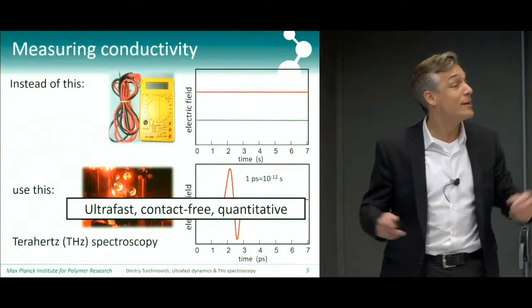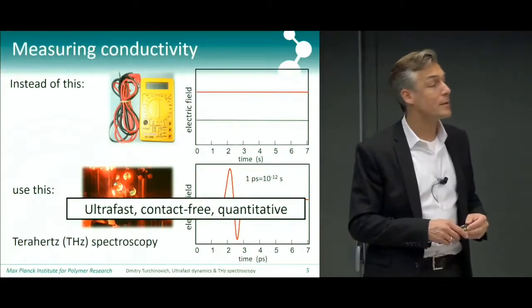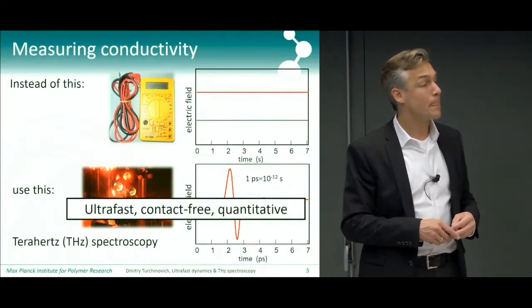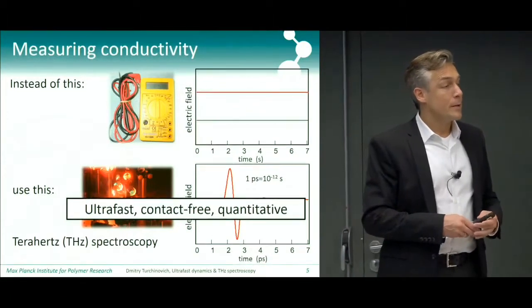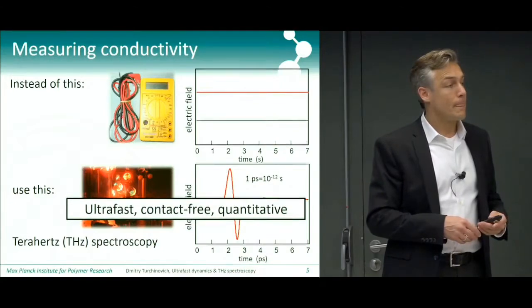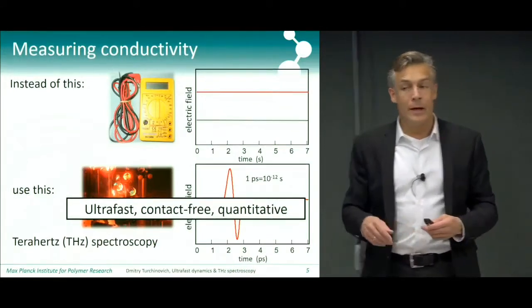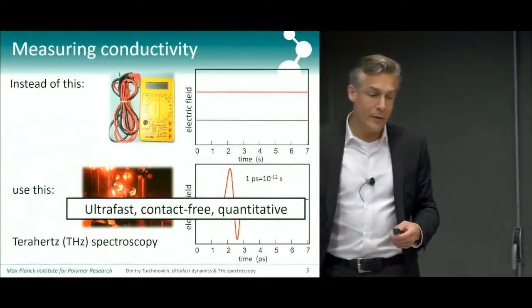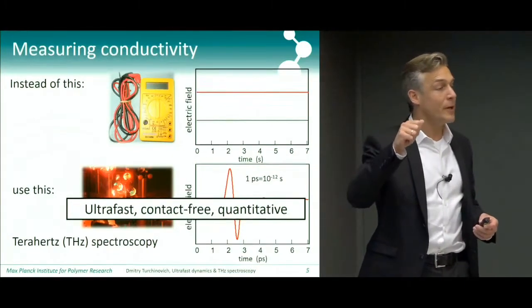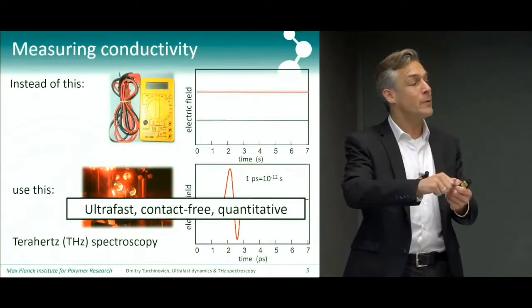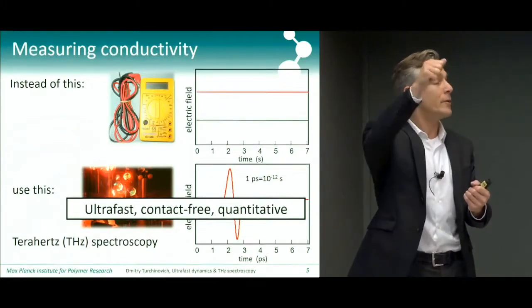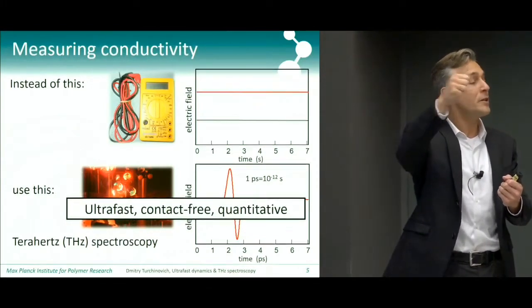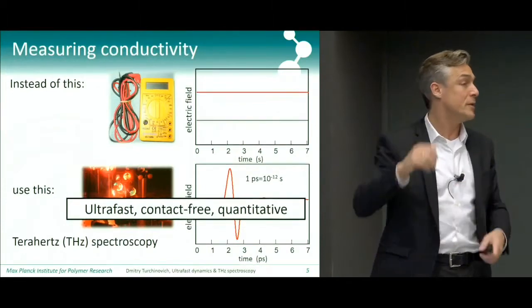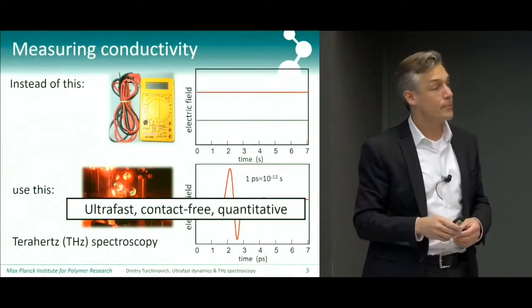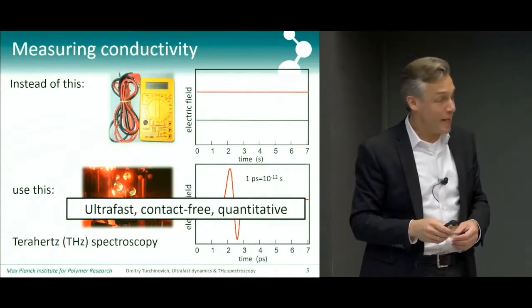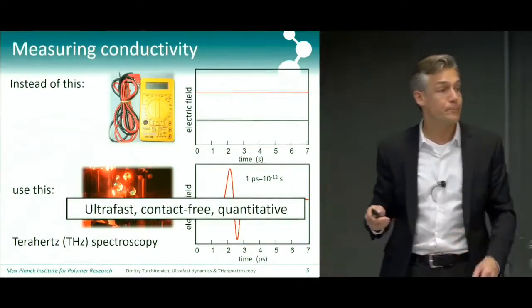Any other questions? So the reduction in the pulse amplitude means it's lost energy. Is that going to motion of the electrons, or is it dissipated? Is it measuring the imaginary part of the conductivity? The loss in the amplitude is indeed dissipated. There's some energy dissipated in the system, and what happens is that the electrons will scatter off of phonons, and that is what is giving rise to the decrease in the amplitude, effectively. So it's measuring the resistivity? Exactly. Yep.